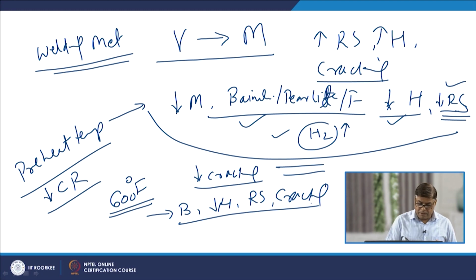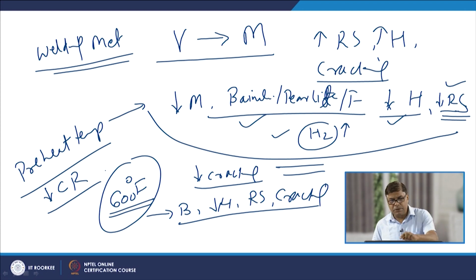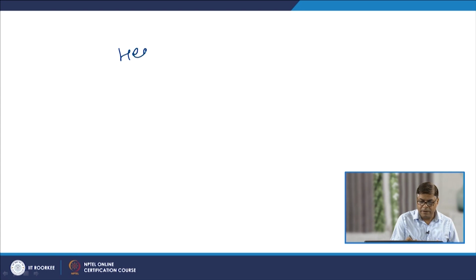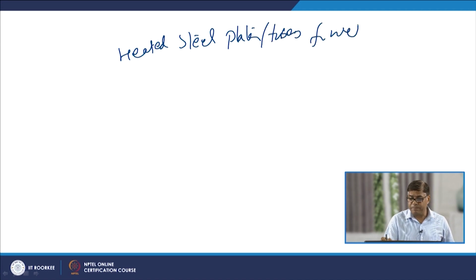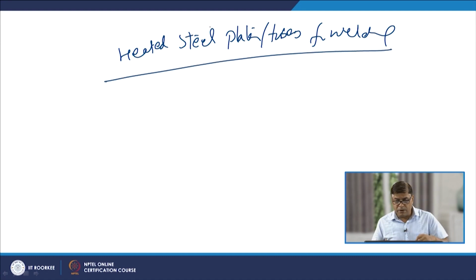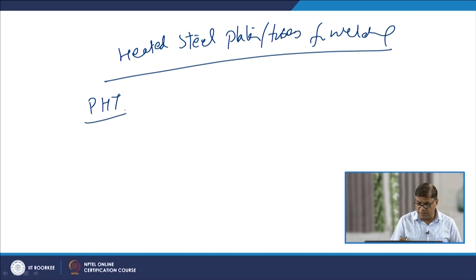But welding of the heat treatable low alloy steels using a higher preheat temperature makes the welding job difficult for the operators, because the operator will be dealing with heated steel plates or tubes or structures for welding. So it is not always appreciated to use a very high preheat temperature, because it makes the job of the welder difficult. So it is important that the preheat temperature is selected suitably, so that the cracking tendency is reduced while there is ease of welding for the operator as well.